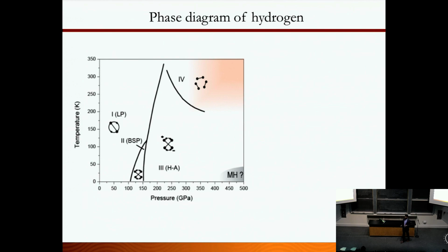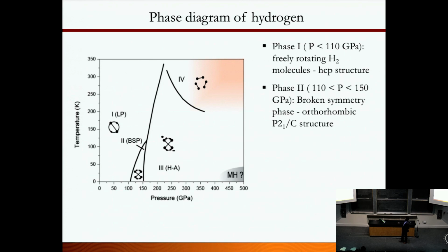So let me give you a little bit of background on hydrogen. This is the low temperature phase diagram of hydrogen. You have four new phases that people have found over the years, most of them found in our lab, and this is the recent one, which was found by the Max Planck group in Germany. We have a low pressure phase, an hcp structure, with freely rotating molecules. Then if you go up in pressure, around 110 GPa, you get the broken symmetry phase, which is stable up to 150 GPa. And if you go above 150 GPa, you get phase III, which has a very interesting property: it gets really strong IR activity.